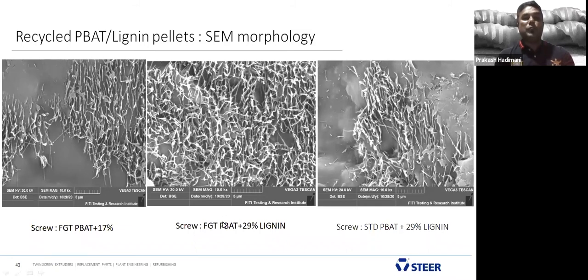This is what we got with FGT technology. We did the same thing for the standard technology, and again we observed lumps. The distribution was not proper in the standard technology. We used the same lignin and the same polymer, only the technology is different. The screw design is different, standard versus FGT. But we observed poor mechanical property in the standard technology.